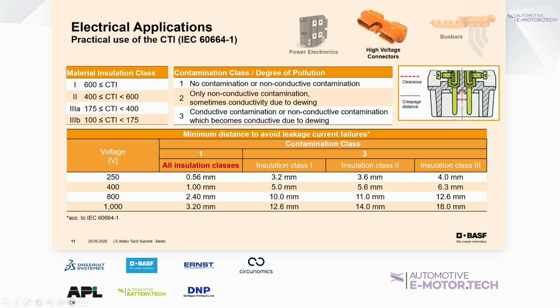But it's important to know that the practical test has nothing to do with the norm, how you use these materials later on in the real part. Because what you typically measure here, according to the norm, is a value up to 600, typically called CTI 600. But it doesn't mean that you can use this material just for applications with a maximum of 600 volt. This is something that is sometimes a little bit misunderstood in the industry.